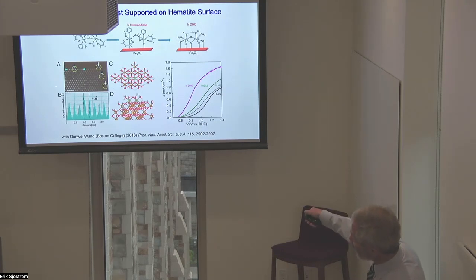And because we can see the lattice structure, this allowed Victor Batista's group and Yang, who's the real expert on computational modeling, to model the structure of the surface using the hematite lattice and the iridium on the surface. And this is a computational model, which looks something like this, where we've got not only stable anchoring of the iridium using the oxygens to the lattice, but also water coordinated as terminal ligands, which we believe are the active sites for the water oxidation reaction.